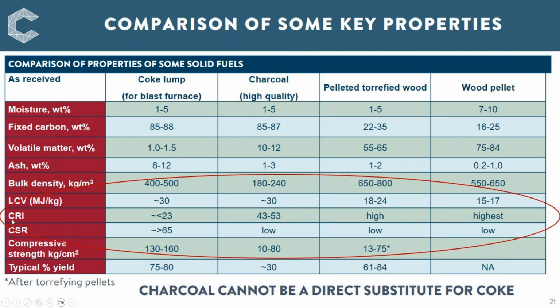We've got this coke reactivity index, carbon reactivity index, CRI, which is the reactivity for carbon dioxide gasification. And for coke, we want this index to be less than about 23, and for charcoal it's much higher. And the CSR is the coke strength after reaction, or the carbon strength after reaction. So as the material gasifies with CO2, it opens up the structure. It makes the strength decrease. But you can see that for coke, it has a high value. For charcoal, it's a lot lower, and the compressive strength is a lot lower, and so on. So charcoal cannot be a direct substitute for coke.